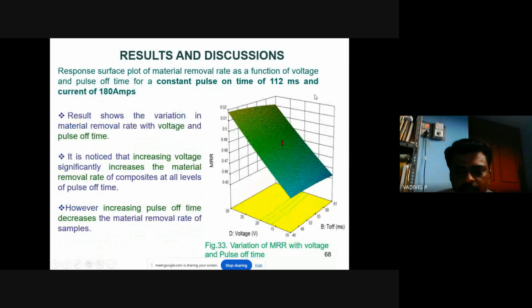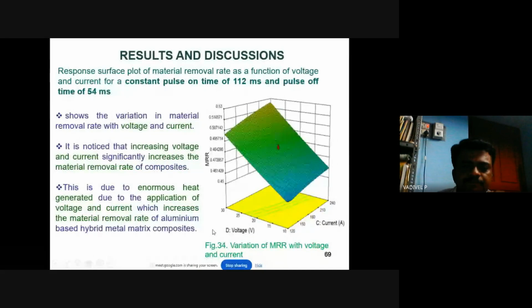This is the plot between voltage, T off and MRR. While increasing the voltage, increasing the pulse off time decreases the metal removal rate. When we increase the voltage and switch off the pulse, the metal removal rate decreases. The next one is the variation of MRR with voltage and current. The plot is between voltage and current. Increasing the voltage and the current increases the metal removal rate.